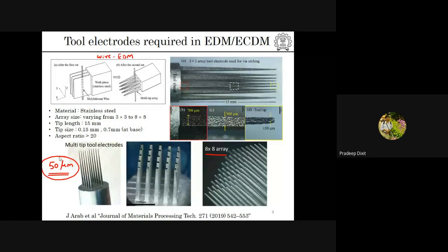When you have this high temperature, you have a lot of thermomechanical stress. And if you look at this picture of the requirement, this length is very high, about 15 millimeter, and here the tip size is very small. So if you try to create a very small tool electrode having a size of 50 micrometer, this tip always has a bending issue. It means that the tip does not remain flat and straight, it becomes bent. Because of this bending issue, the minimum size which we are able to fabricate by using iridium is 100 micrometer.